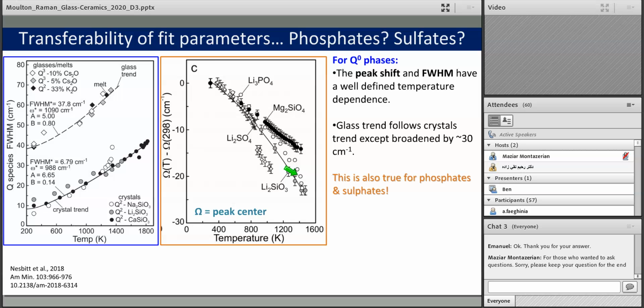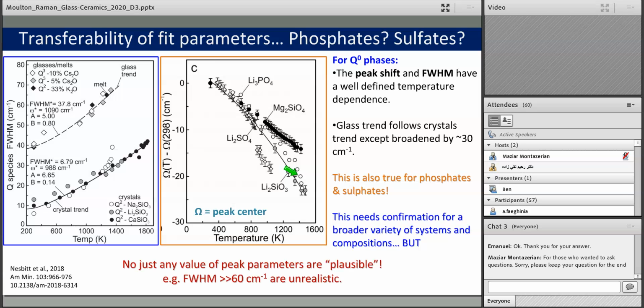But all this is pointing to the fact that these stretching vibrations, whether it's silicon oxygen, phosphate oxygen, sulfate oxygen, have similar physical parameters that tie the crystals and the glasses together. And hopefully more people will use these parameters so that we can make our fits not just reproducing the envelope that we saw earlier, but have the physical parameters expected of the same vibration going from the crystal into the glass.